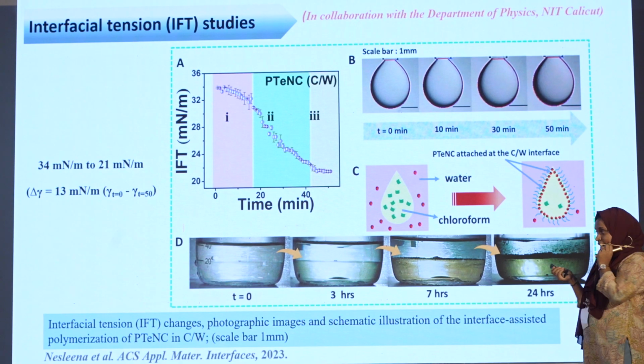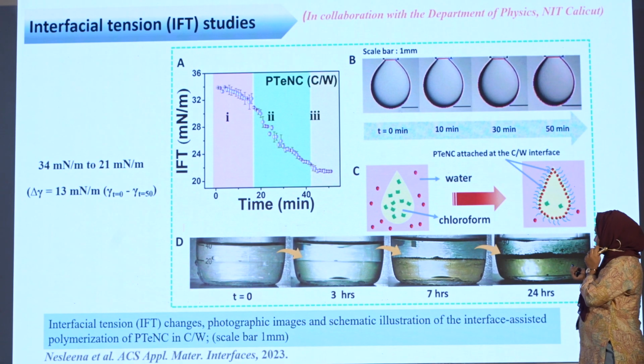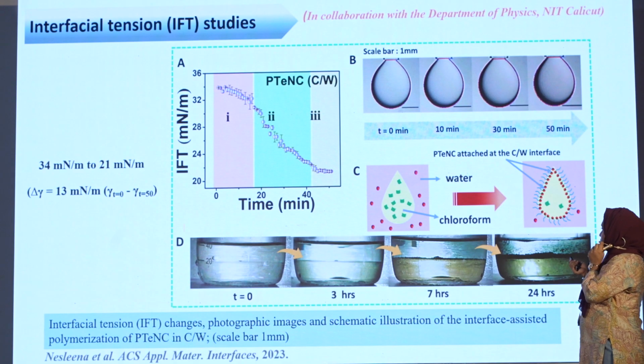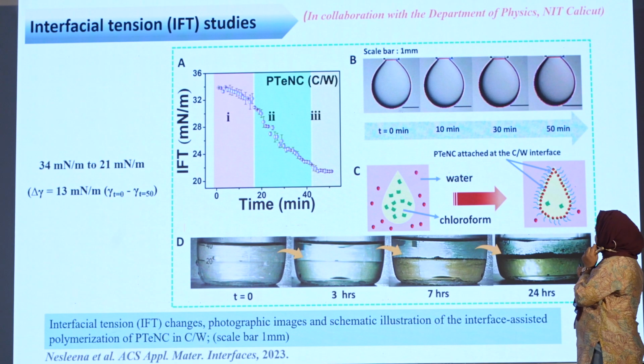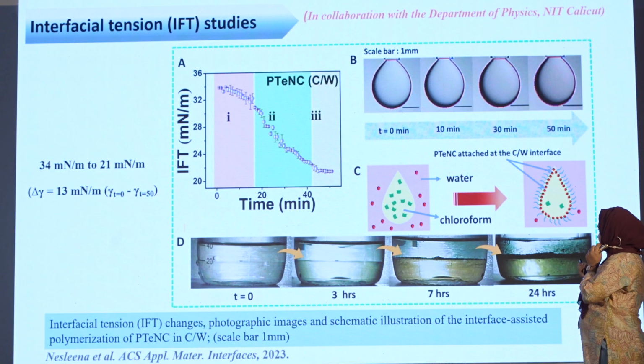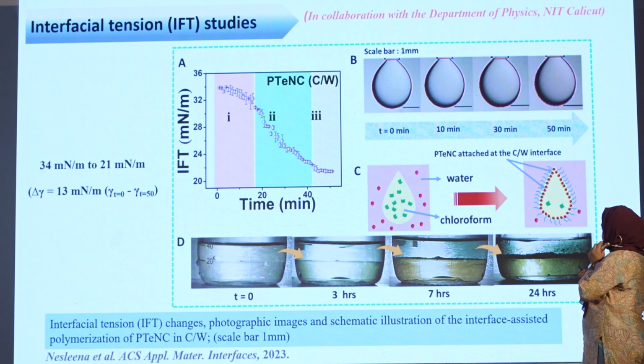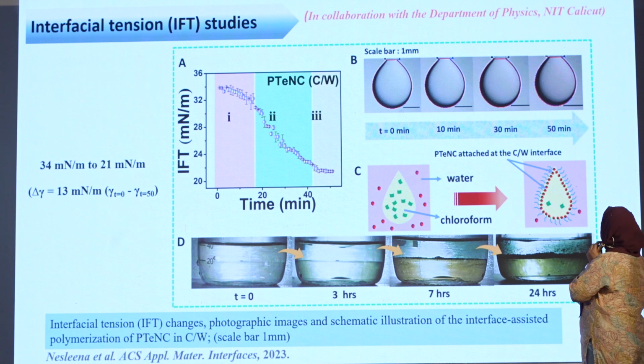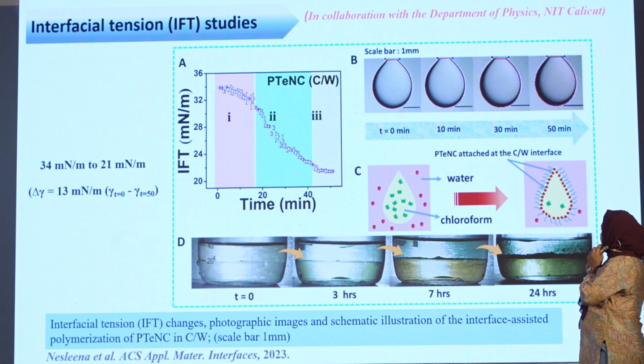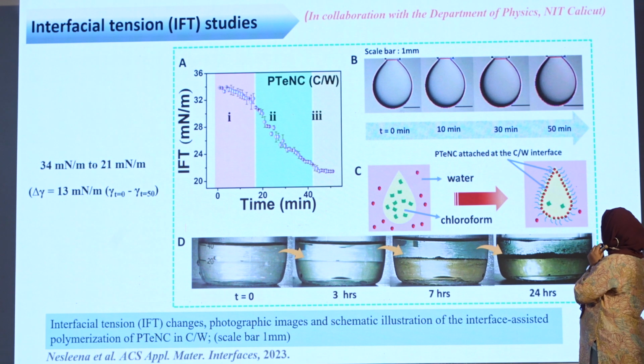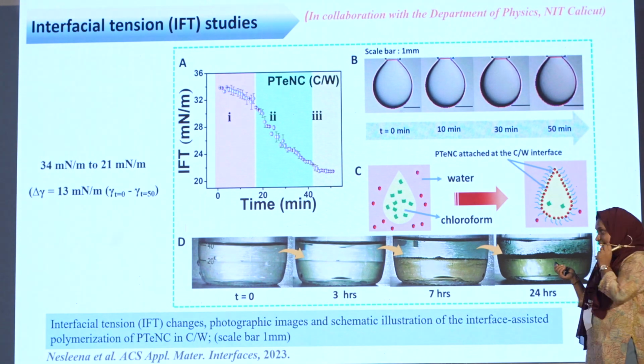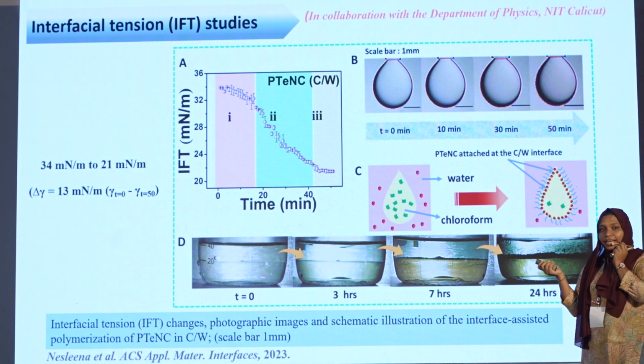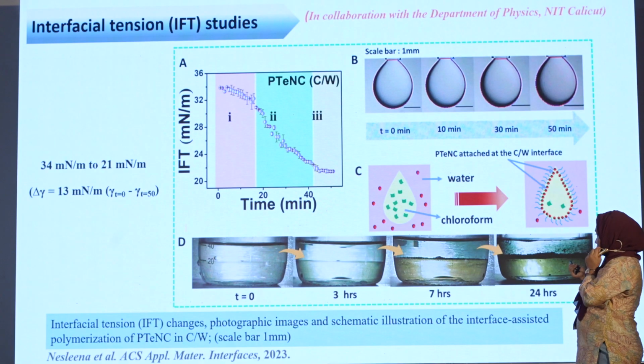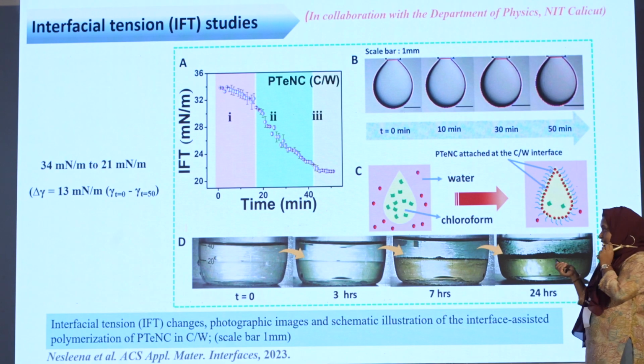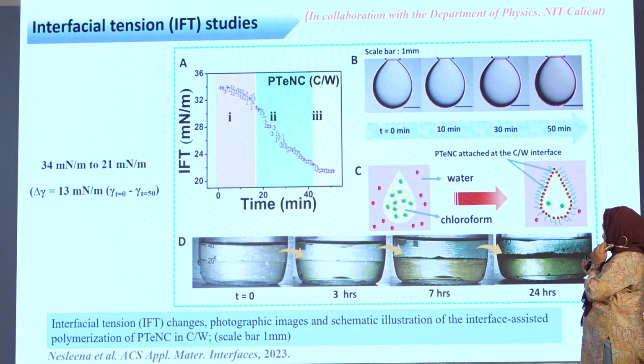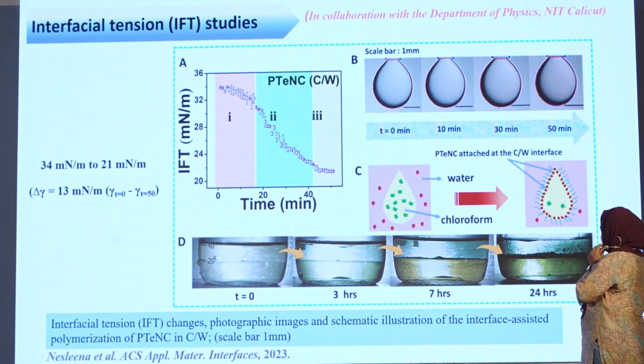We analyzed the interface confinement as well as bulk confinement using interfacial tension studies using pendant drop tensiometry in collaboration with the Department of Physics, NIT Calicut. We have seen interfacial stabilization for the chloroform-water system up to 50 minutes. The drops were stable up to 50 minutes, and the corresponding fitting images after the pendant drop technique are also shown along with the schematic illustration. The experiment that we conducted on the lab scale for 24 hours for comparison is in good agreement with the results obtained from pendant drop tensiometry.